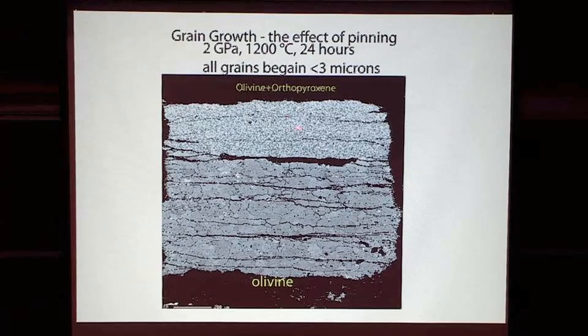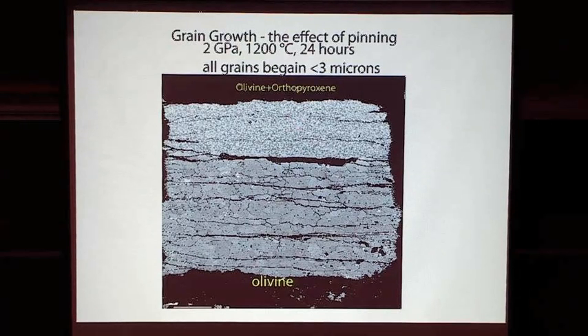They're gigantic, right? The grain boundaries in an olivine-olivine aggregate migrate very, very fast. They just have to exchange isochemically with one another, and so you get incredible grain growth in a monophase aggregate. And maybe this does apply to the inner core, but it certainly isn't what the mantle is made of. Whereas in a real rock, in order to affect grain growth, you have to actually diffuse composition. For olivine and orthopyroxene, you have to move silicon around in order for one grain to grow at the expense of another. And as a consequence, the properties of grain growth and associated things with grain boundary migration are very much controlled by the texture of the material, the fact that it's a rock as opposed to a monomineralic aggregate.